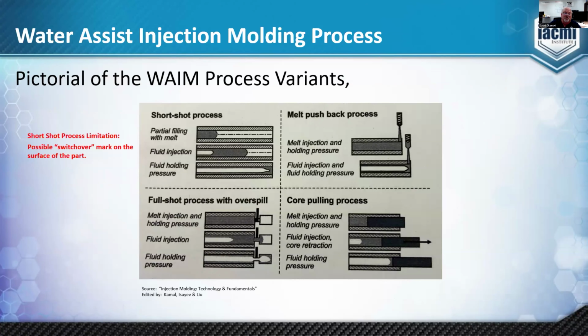This is a pictorial of each of the processes, short shot and the full shot process. So you can see here in the short shot process, we're stopping, filling the cavity short of being full. Water is injected, and that water will push the flow front to the end of flow, filling out your cavity, and then you're using the fluid pressure to pack.